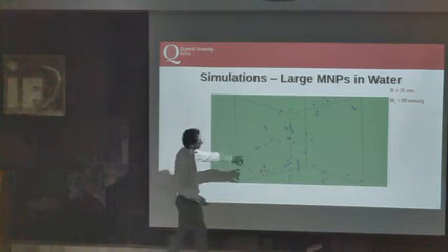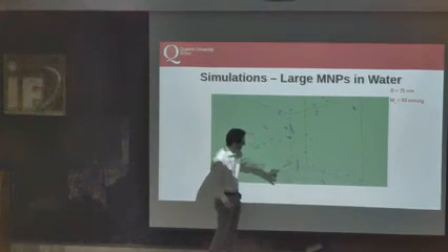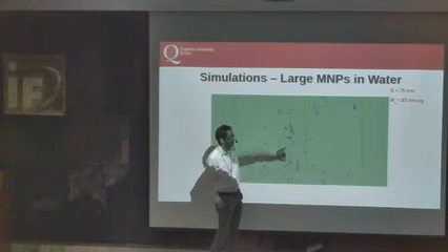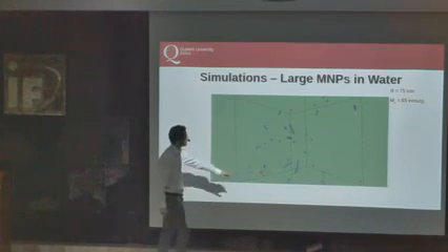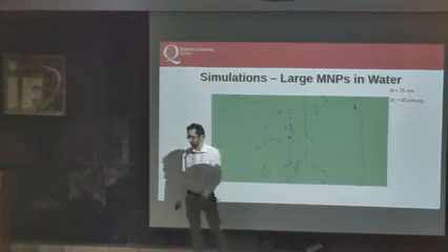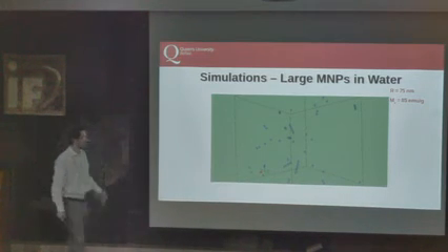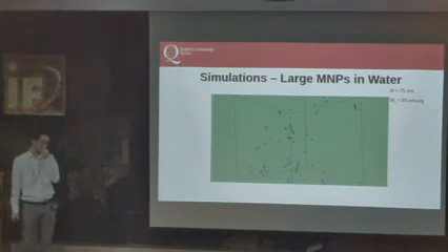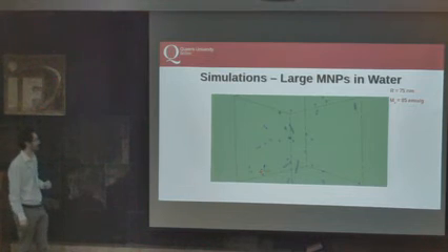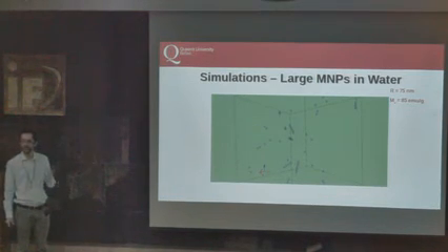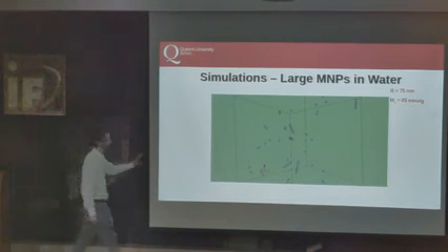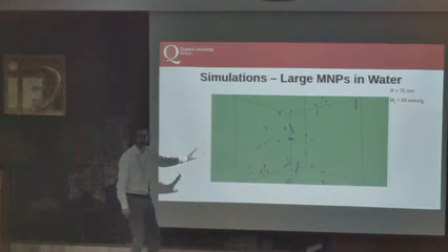And towards the end of the simulation, you see that there are quite a few chains. And here is another event. Those are very long simulations. This is why we had to use so far just a few nanoparticles. Those are 55 nanoparticles. But the concentration is the experimental concentration.